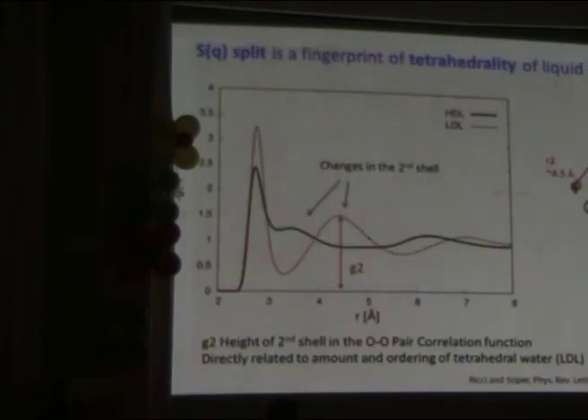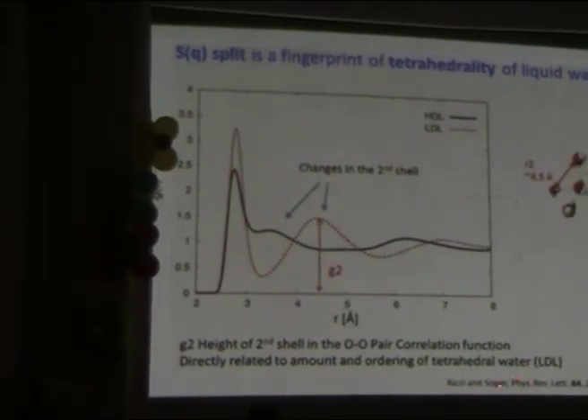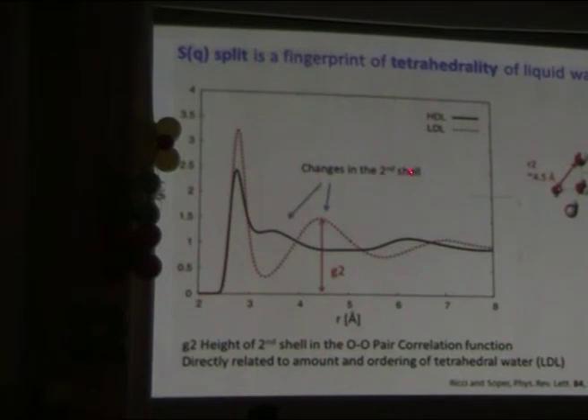We want to extract more information from the experimental data. We want to be able to say something about the tetrahedrality. We need some parameter, and what we will use is the height of the second shell, which we will call G2. Here are experimentally derived pair correlation functions for high-density liquid and low-density liquid. This is from neutron diffraction data by Ricci and Soper.